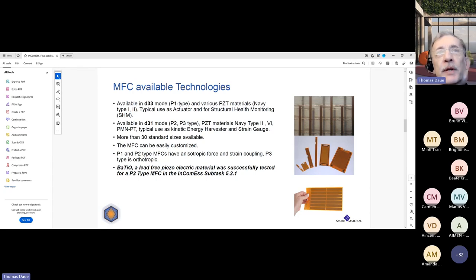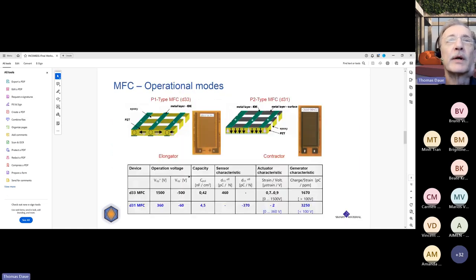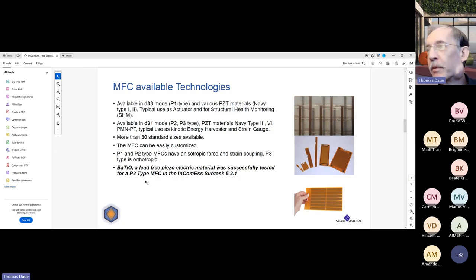And in the 5.2 work package, we also tested barium titanate, a lead-free ferroelectric or piezoelectric material, more to comply with RoHS. But the performance is still so far behind. The prices are still very high. It is not really expected that lead-free will be any competition to PZT in the next couple of years. That's just the current situation. The exception for RoHS will probably be continued. And honestly, the rest of the world does not really care about it. Since we are exporting to more than 35 countries, it's always interesting to see those different markets.